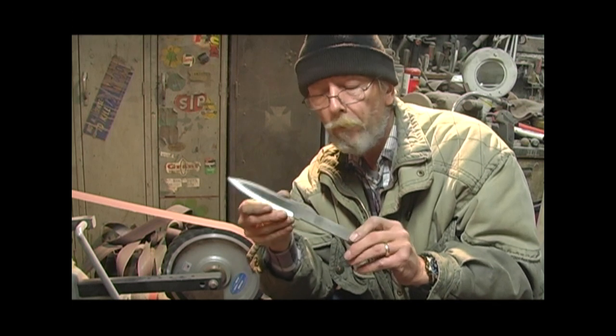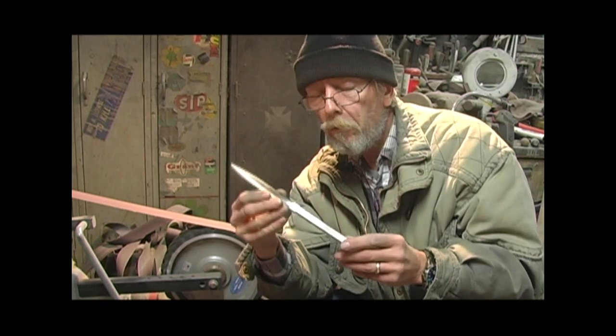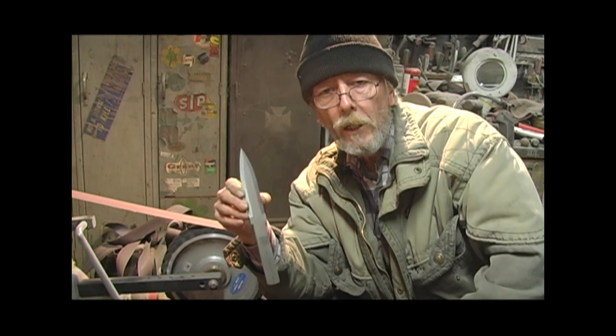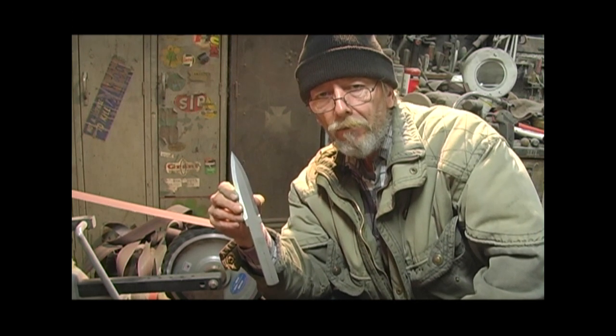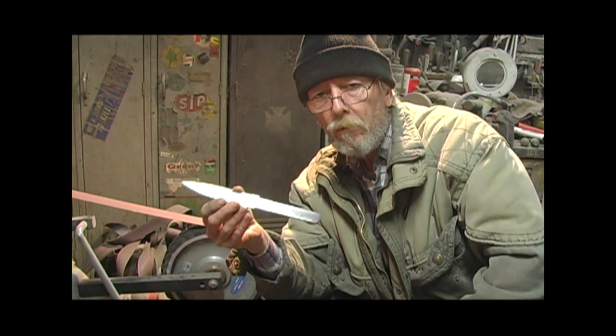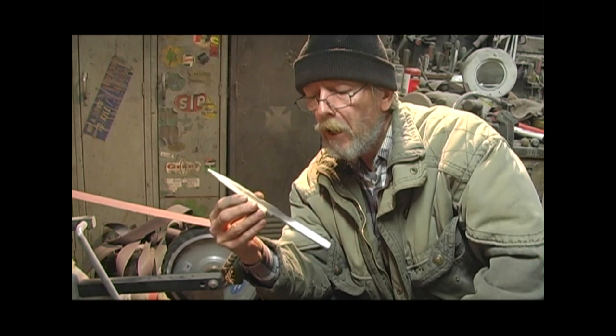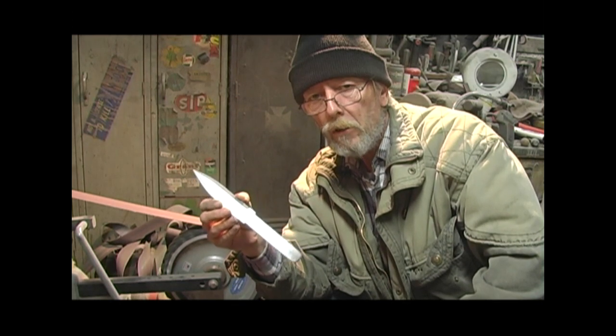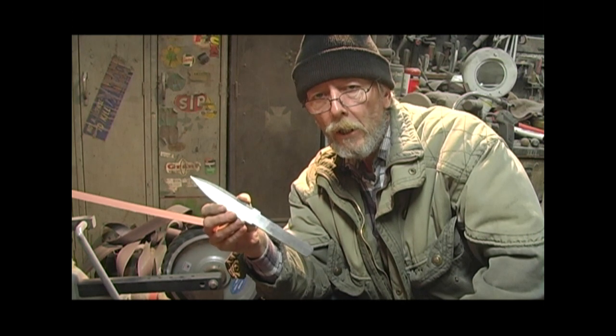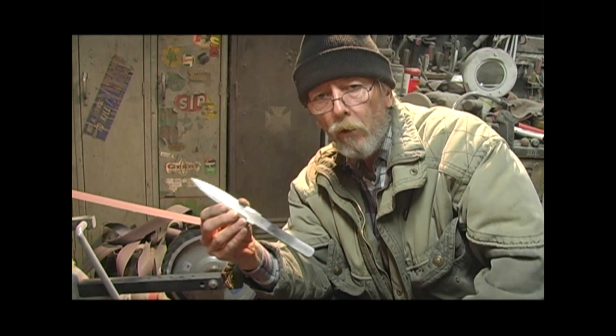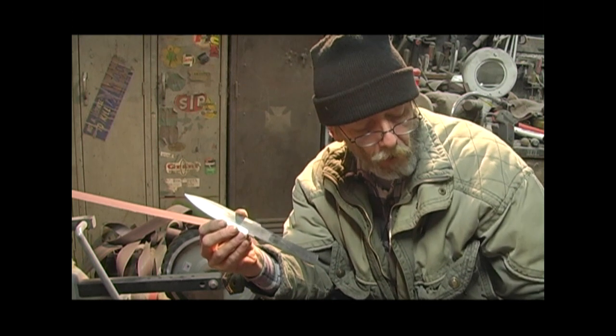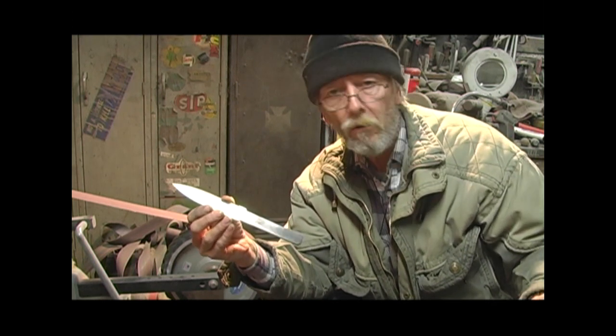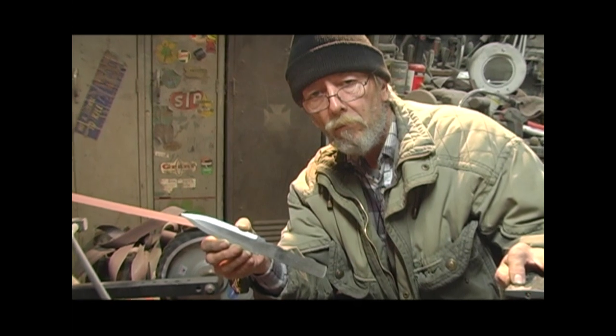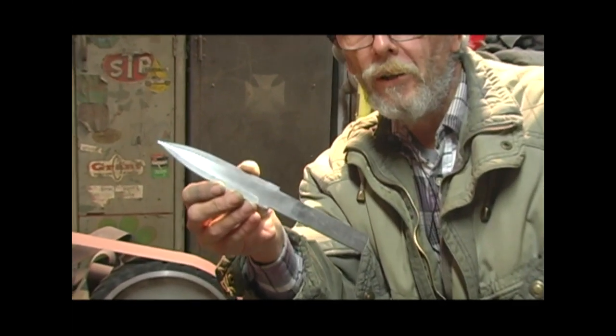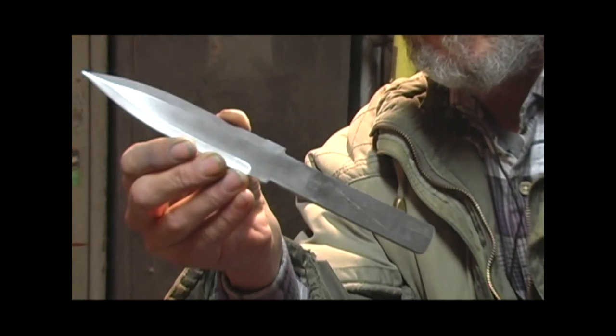But I have ground this at 60 grit and then came back and refined it with the 220 grit. I used to go from 60 to 120, but I found that with annealed steel, when it's still in its relatively soft state, I can jump from 60 to 220 grit, and it just saves wearing out a few belts. You might have to make a few more passes with the 220 grit, but it works fine for me. But here we are.